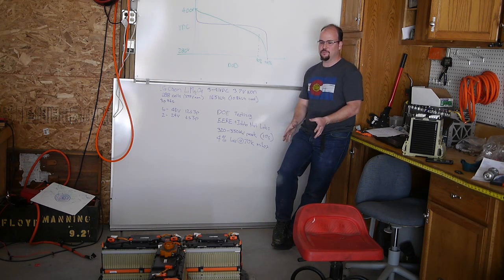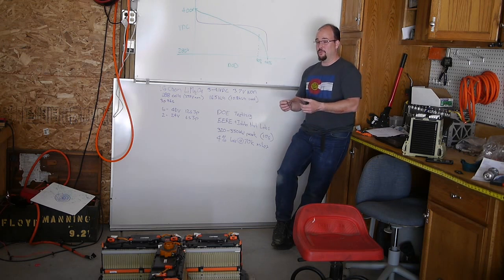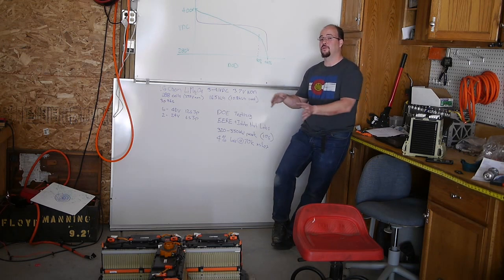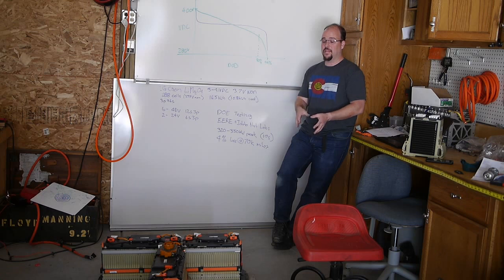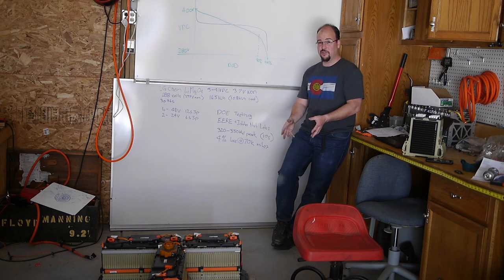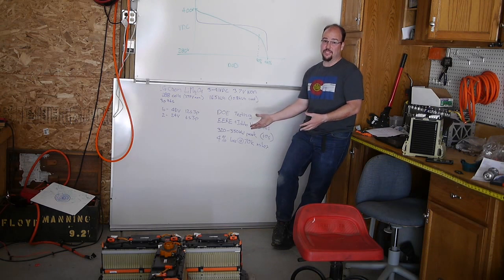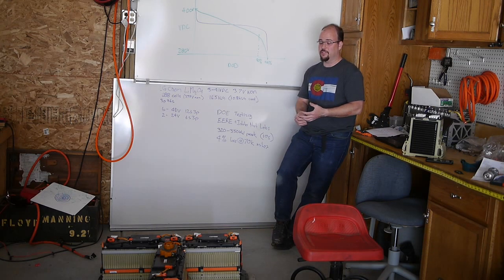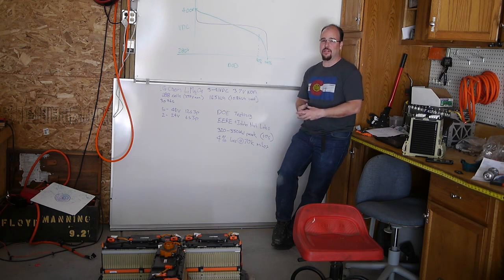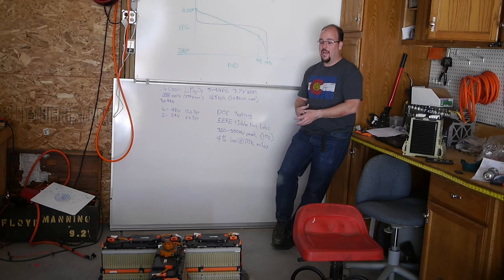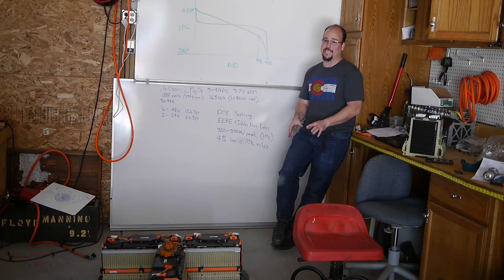The most interesting thing for me is they actually do peak power testing. Now, I've been reading through the different test procedures they have. There is one for plug-in hybrids, and then there's one for EVs. The plug-in hybrids standard, REV2 is the only standard that's been released. Apparently, they've been doing testing to REV3, which isn't yet released. REV2 does an 8-second pulse, but in the test reports that I'll show you the links to, they clearly say it's 10-second pulse. And depending on the battery, the highest that they've been able to record is about 350 kilowatts.